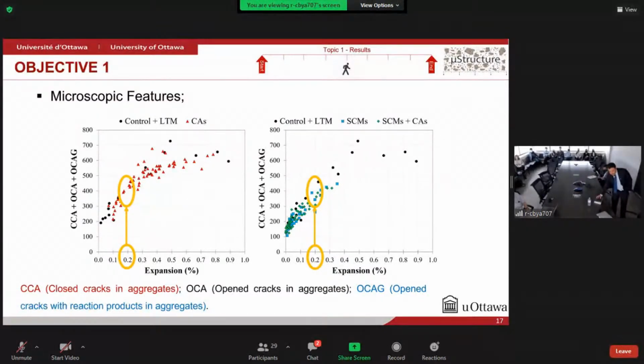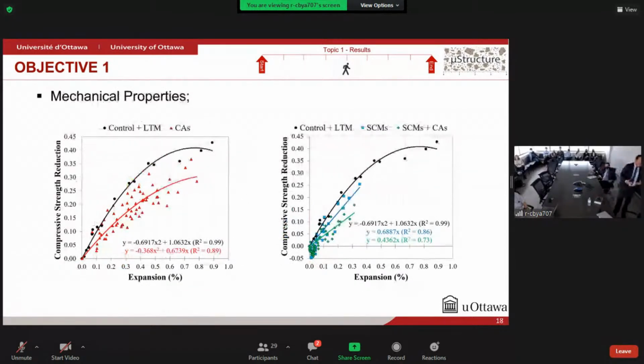To evaluate that, we then check mechanical properties that are cement paste based dependent. And as we can see here, using crystalline mixtures or mixing them with SCMs, we can see a clear sign that for a comparable expansion amplitude, they can reduce the compressive strength loss. But also we can see that once we use only SCMs in concrete, we also had such a decrease in compressive strength loss. So why did we have that? We are not using crystalline admixtures here.